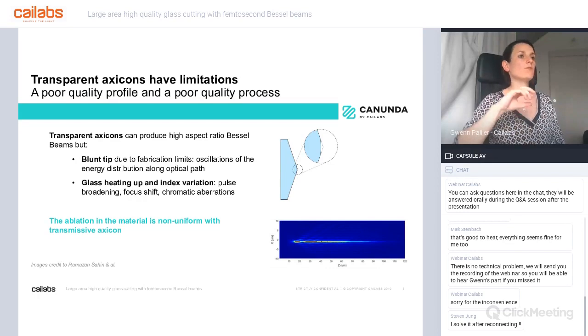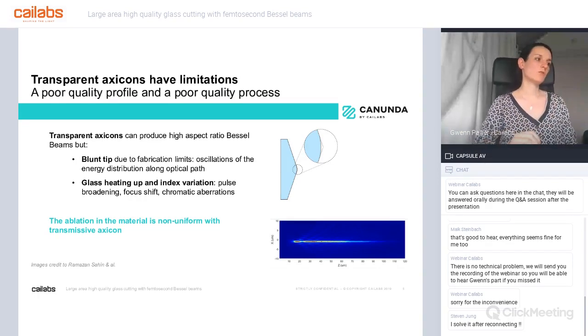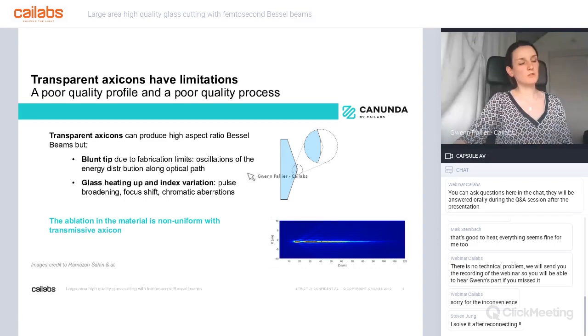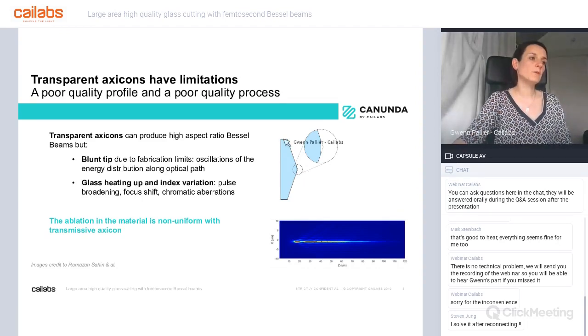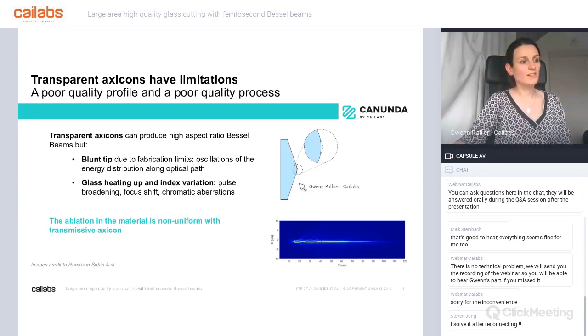I would say that basically you have 2 main limitations. The first limitation is the blunt tip. The way you manufacture these transmissive AXICONs, you always have a round tip at the top of the AXICON, and then you have a part of your beam which is getting out with a conical face, and a part of the beam which is getting out with a spherical face, a small part of the beam, but still a part of the beam. And both these 2 parts of beams will interfere as well, and they will create oscillations. You can see them along the optical axis over there.